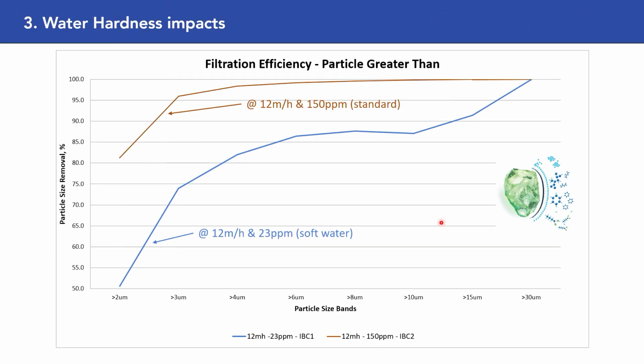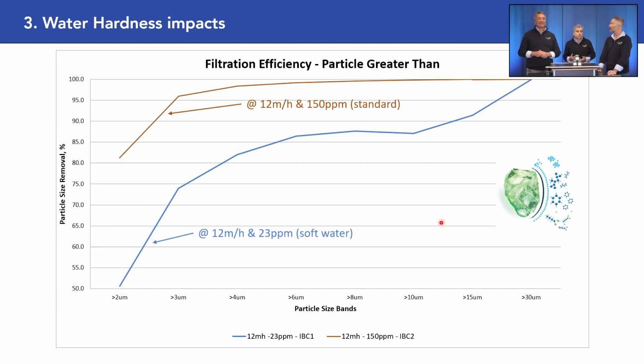Good. Number 3, water hardness. What is the impact of this? Water hardness is a bit surprising. For the previous ones, we could expect some influence on the performance, but not for water hardness. We see again on the axis the particle size bands, and we see 2 charts. One with a standard hardness of 150 ppm. Quickly for the audience, for those more familiar with French degrees or German degrees, that would be 15 French degrees, roughly 9 German degrees, and also 150 milligrams per liter.